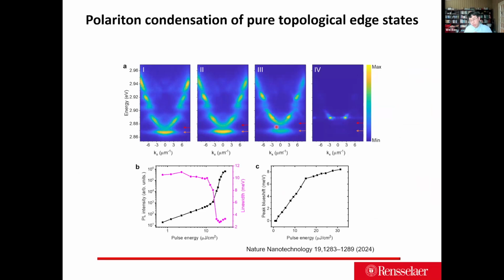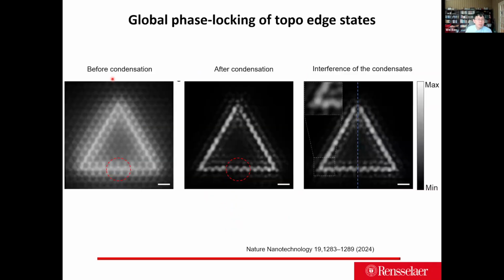And then, due to the interaction, the whole system blue shifts, which indicates our photons are interactive because of their polaritonic nature. Then there is the blue shift, the condensation, and the linewidth narrowing. And if you do a G1 interference by taking the image after condensation, taking the left-hand image and then flipping it, and doing the imaging interference, you will see interference fringes start to show up. This is before condensation, this is after condensation, and this is the interference starting to show up.